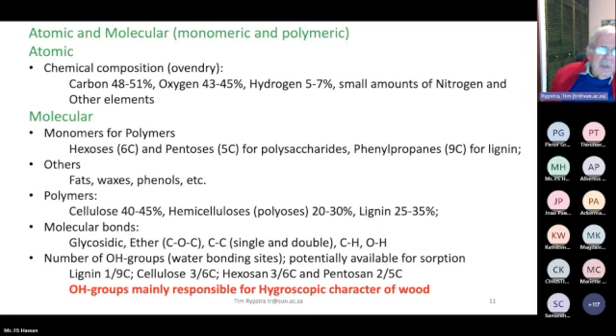And actually, we are interested in the number of hydroxyl groups, or the water bonding sites, which are potentially available for sorption. In lignin, the one component, there is 1 site. In cellulose, there are 3 per monomeric unit, there are 3 for the 6-membered and 2 for the 5-membered units that make up the wood. So the hydroxyl groups are mainly responsible for the hygroscopic characteristics of wood.